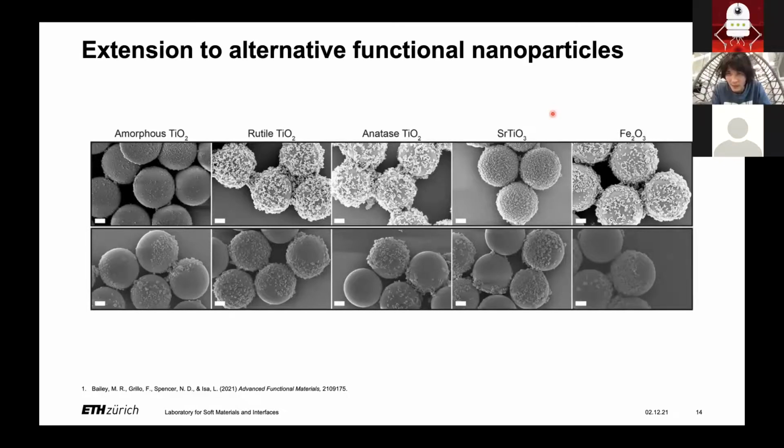For example, if you want to attach gold nanoparticles for thermophoresis, instead of nitro catechol, you can put in a thiol group. The thiol would have to be protected probably initially, but that would be fairly straightforward. And then remove the protection, and then you have a thiol group, which you can then bind very well to a various range of noble metal nanoparticles. So really, this approach gives you the option of attaching different types of nanoparticles.